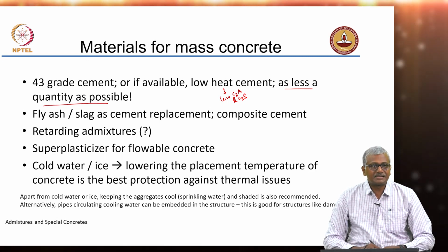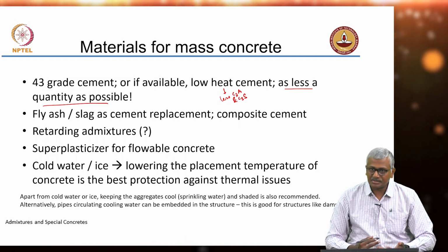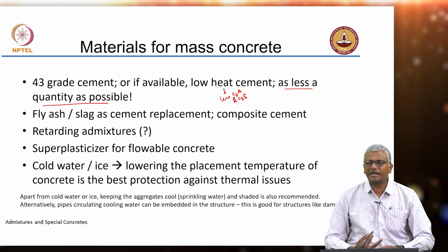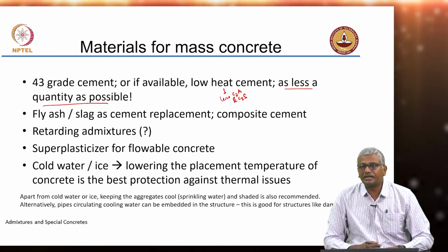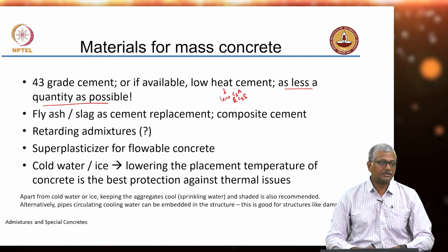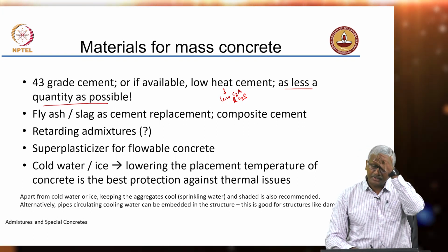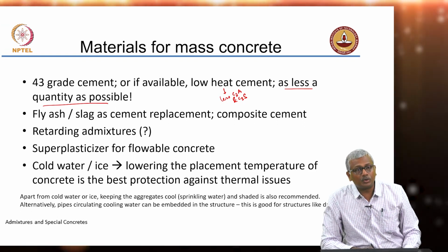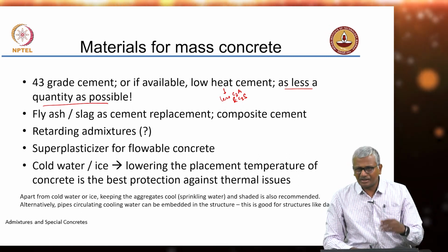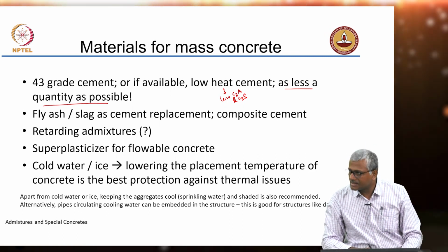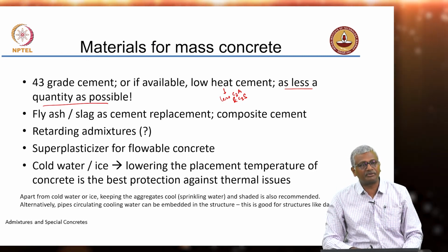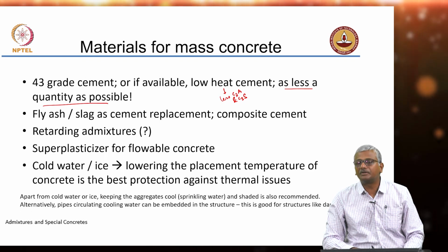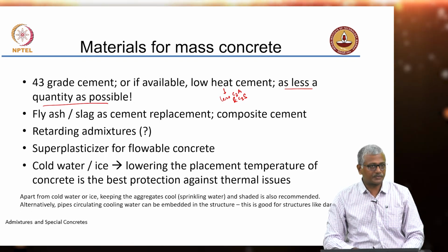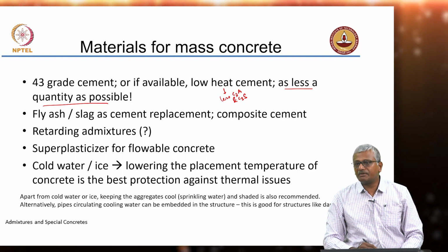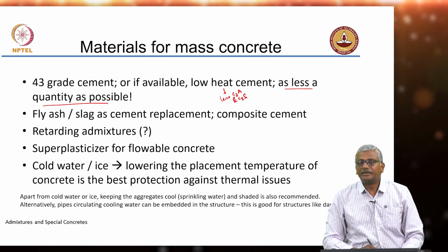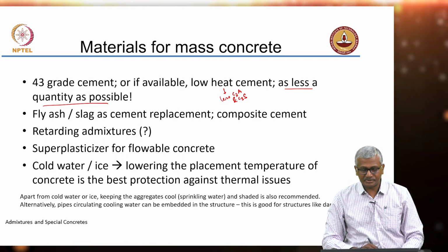Fly ash or slag as cement replacements are almost always a must to do that, especially fly ash, because slag does not have as much of a drastic heat reduction effect as fly ash, right, because most of the slags that are available in the industry are of a fineness that is equal to or more than cement, because of which their reaction could be quite fast. You may not really get significant reduction unless you go for very high percentage replacements, 50-60% replacement, then you will start seeing the benefits of slag also. But fly ash even at 20 to 30% will lead to a major reduction in the overall heat that is coming from the system. Okay.